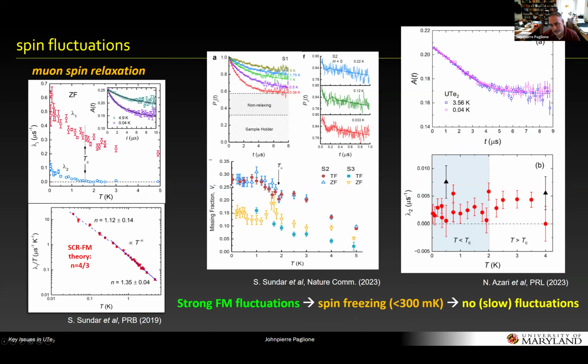Okay, μSR. So next study, and this has to do with spin fluctuations as well. So the early work, which was when we were collaborating with Jeff Saulnier's group, in the first generation of samples, we saw a very, very large muon spin relaxation rate upon cooling. And it was large enough that it was very hard to see what, if anything, was happening in TC. So this question about whether there is a time reversal breaking signature in μSR was impossible to answer. Interestingly, if you fit the relaxation rate to a spin fluctuation theory, you actually get something consistent with the ferromagnetic incipient ferromagnetic critical point scenario. And so that was the first observations. And also note that there were two relaxation rates that came out of the analysis of the data, which we didn't quite understand at the time.